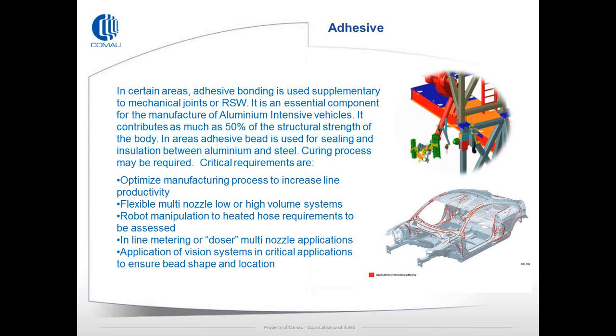Some critical requirements are, because of the application speed of the actual adhesive, the overall manufacturing process needs to be fully understood. Flexible multi-nozzles for low, medium and high volume solutions. Robot manipulation to heated hose requirements to be assessed in terms of access and durability. Inline metering and dosing of multi-nozzle applications is more commonplace now. An application of vision systems in critical areas to ensure bead shape and location. And as I mentioned earlier, in particular where you've got dissimilar metals being joined together, and the adhesive bond is being used as the separator. Here, it's imperative that a good and consistent bond is applied.